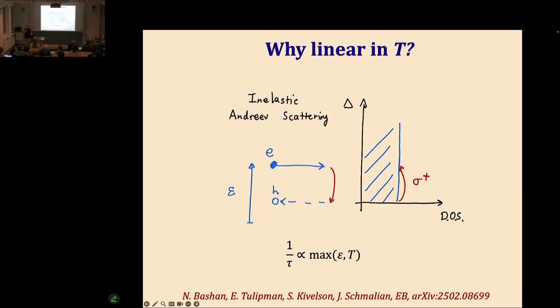The other question is, down to what temperature would this behavior persist? It won't persist all the way down to zero temperature. It would actually be cut off. There are different mechanisms, but the one we think is ultimately dominant is basically the Kondo effect. You think about the two-level system coupled to metallic electrons, that's a little bit like a spin impurity in a metal. And you know that there's the Kondo effect, so the fluctuations of the two-level system would eventually be cut off by the Kondo effect. But we identified a parameter regime where that can happen, and only at an extremely, extremely low temperature.